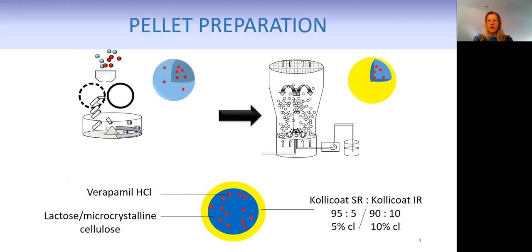So we prepared our coated pellets like this. First, the starter core. We had an equal mixture of lactose and microcrystalline cellulose that was mixed with 10% of verapamil hydrochloride, wetted, and then extruded through a cylinder extruder. The small cylinders were subsequently spheronized and dried. So we obtained small, spherical beads of around 1 millimeter in size, which were then coated in a fluid bed coater with a Wurster insert.